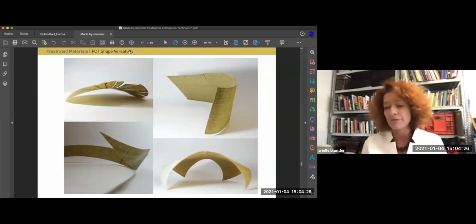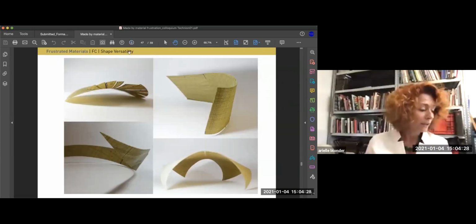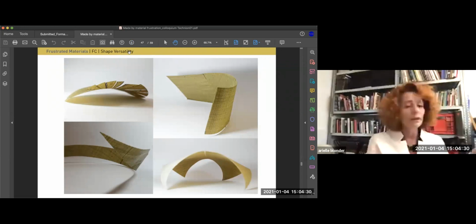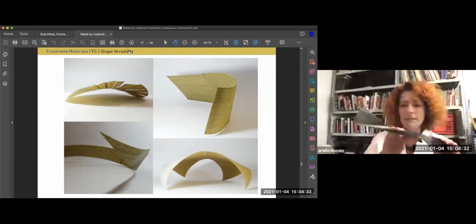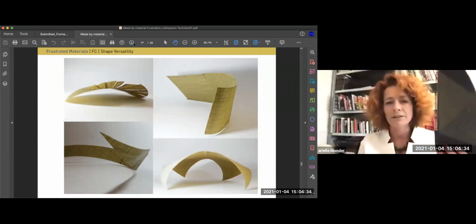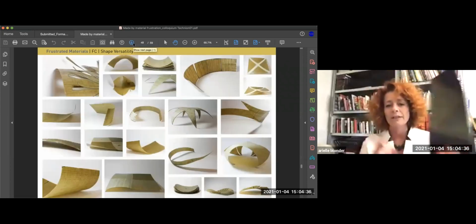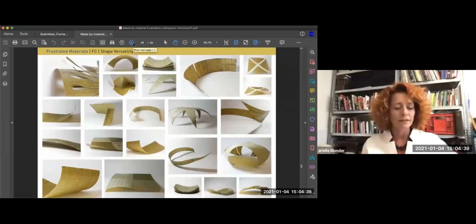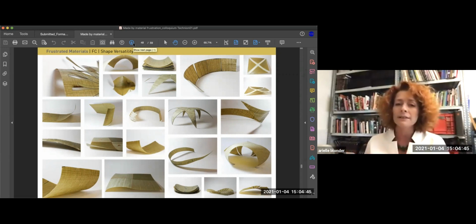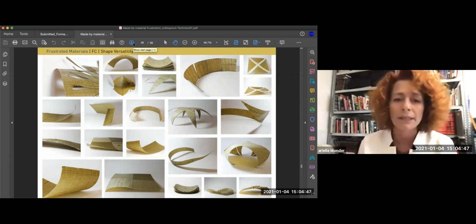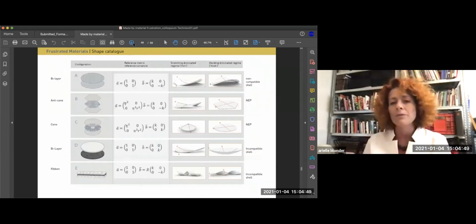And here you have an example of shape versatility in the composite material. So it would look like this. These are elements that enter flat into the oven, and after 2 hours you take them out and you get the shape. Of course, it's always a combination of at least 2 layers of fibers that are not identical, and each of them wants to do something else.